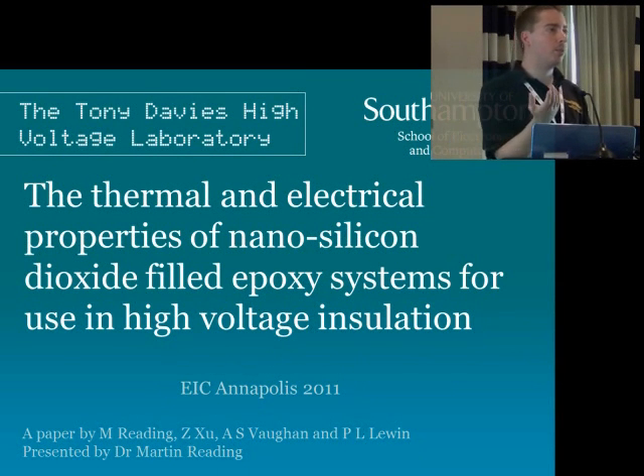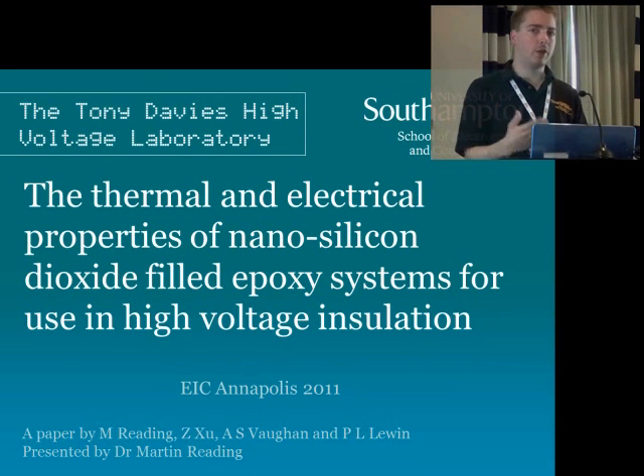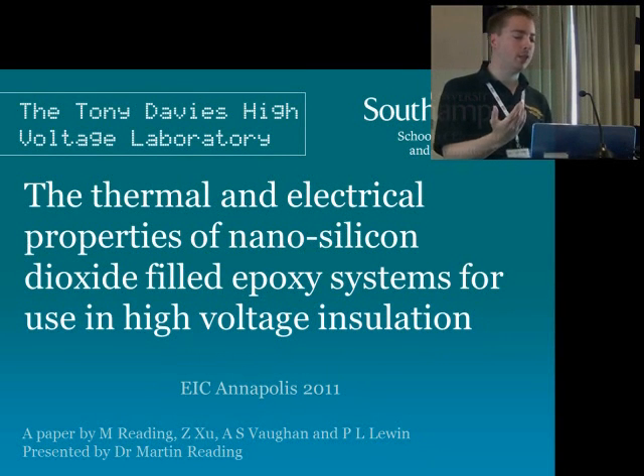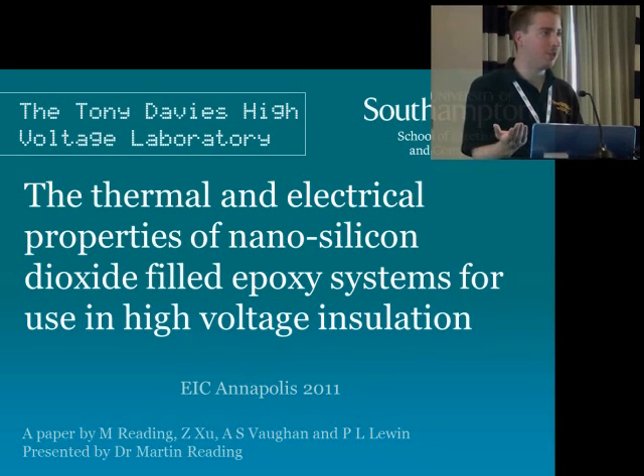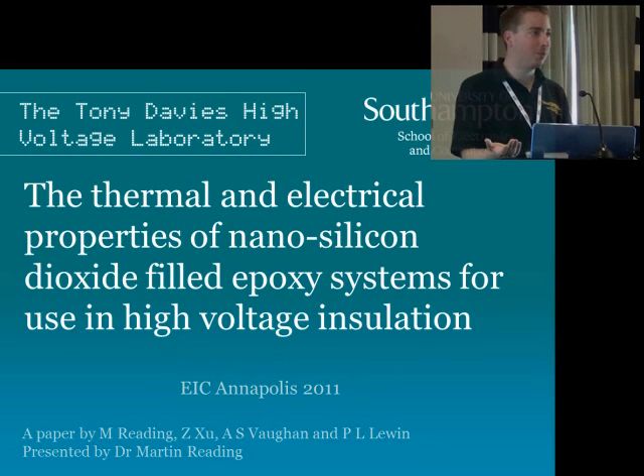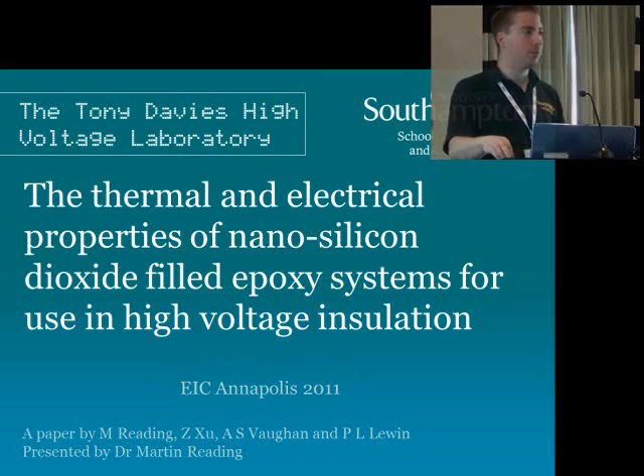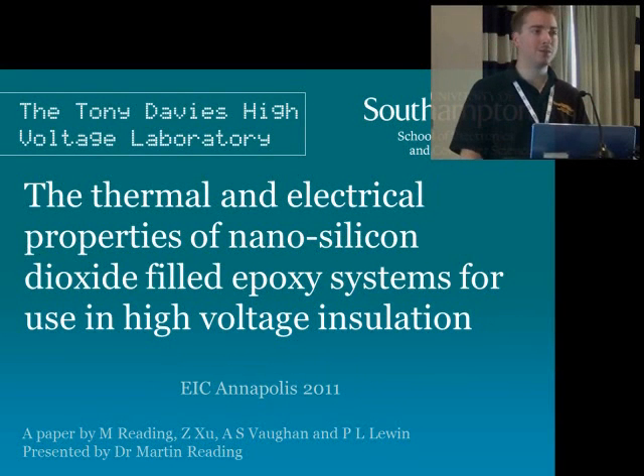Okay. Well, the consideration with that is that we cure our epoxy at around 100 degrees, which for a large number of epoxies is quite low. Whereas the temperature we believe that we'll need to drive the water away from the filler is probably going to be at least 120, 150. So if we did that to the filled epoxy system, we'd then be giving it a post-cure. So we have to then do that for all of the samples. So it might be a lot easier for us if we bake the filler and then add it into the epoxy for the standard cure. Okay, thank you for your question.